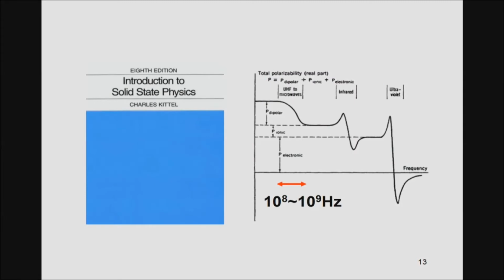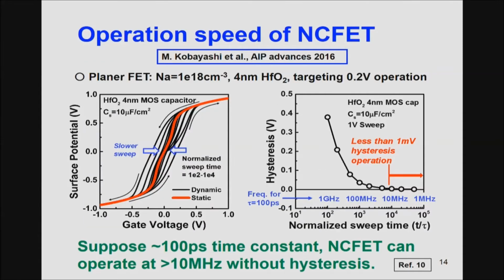The second interest is how fast this NCFET can operate. As I learned from undergrad solid-state physics from this book, dipolar polarization can respond up to microwave frequency. So this may limit the operation speed of the NCFET. I simply included some time dependence in my model, and simulated surface potential versus gate voltage as a function of the sweep time of the gate input. This result summarizes the hysteresis voltage as a function of normalized sweep time. Supposing a 100 picosecond time constant of polarization switching, the NCFET can operate faster than 10 megahertz, which is good for IoT application.